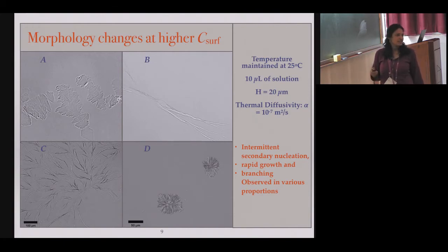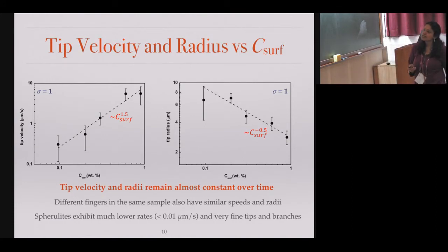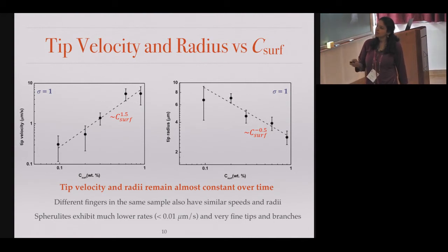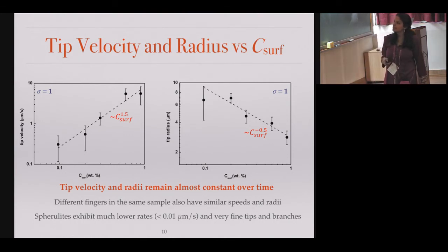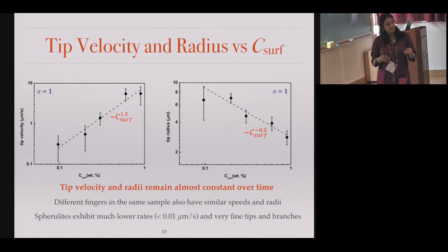The thicknesses of these projections are becoming finer and finer as the additive concentration increases, and the tip velocity seems to be growing faster. We quantify these statistics: on the left is a graph of tip velocity versus additive concentration and we find the velocity increases quite rapidly with surfactant level. If you plot the tip radius — these are very fine crystals so the error bars are high — you can clearly see the tip radius is decreasing with surfactant concentration. The spherulites are not in this picture because they are too fine to track with our microscope. All other systems are at a fixed concentration of the solute, stearic acid.